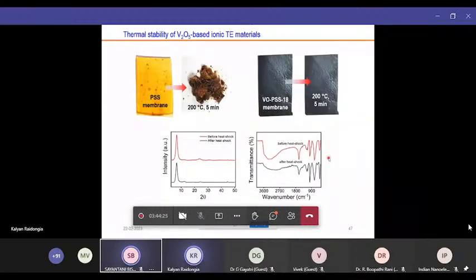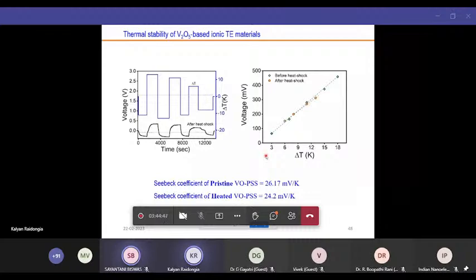Now, as we said, this PSS membrane, a polymeric membrane, shows very good thermoelectric properties, but if you heat it to just 200 degrees centigrade for 5 minutes, it is completely destroyed. There is no question of measuring any thermoelectric properties with this membrane. But our membrane, if we heat it to 200 degrees centigrade for 5 minutes, nothing happens. Its structure is intact as well as its performance. So this is a very good advancement in that direction.